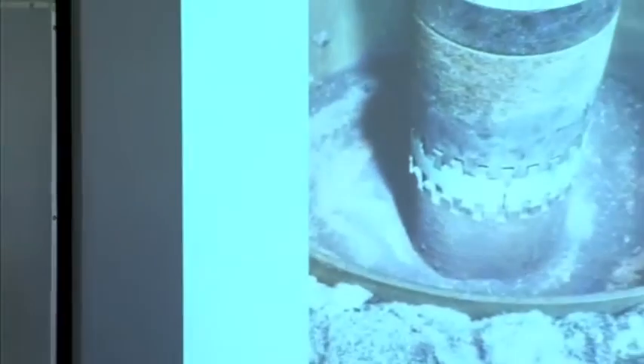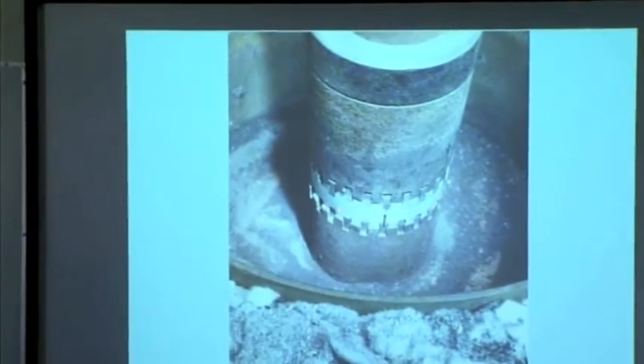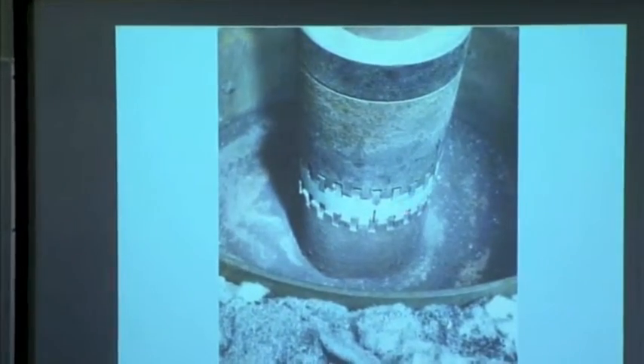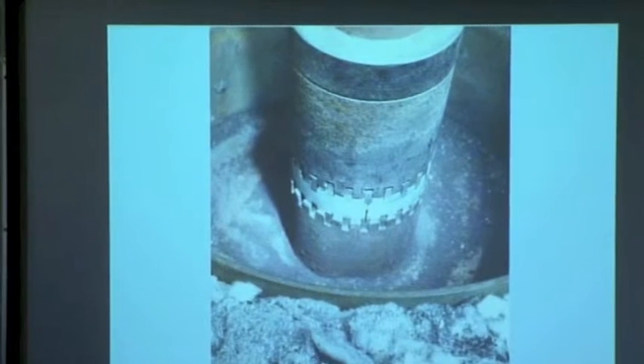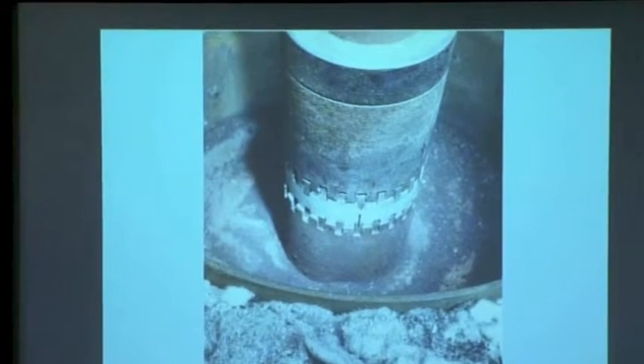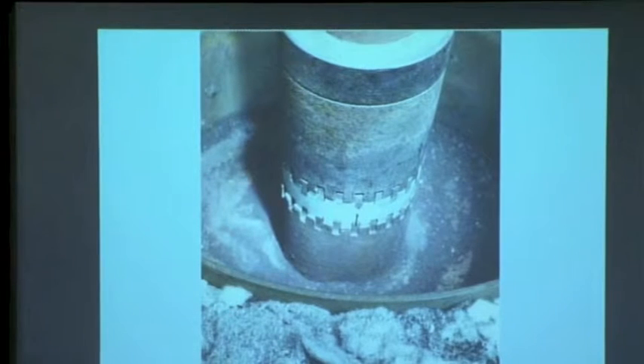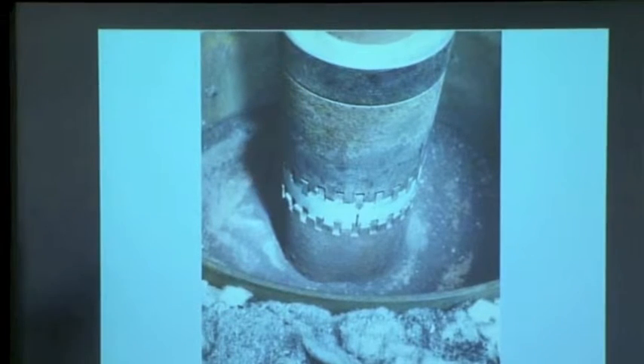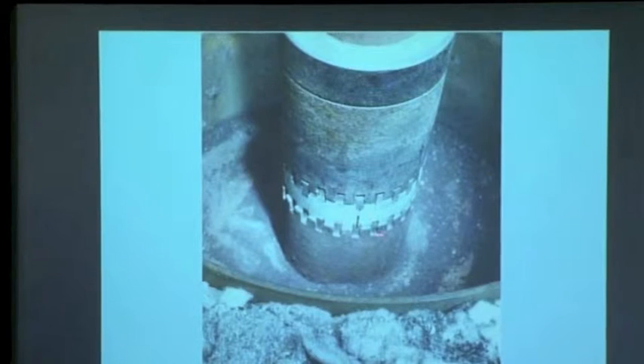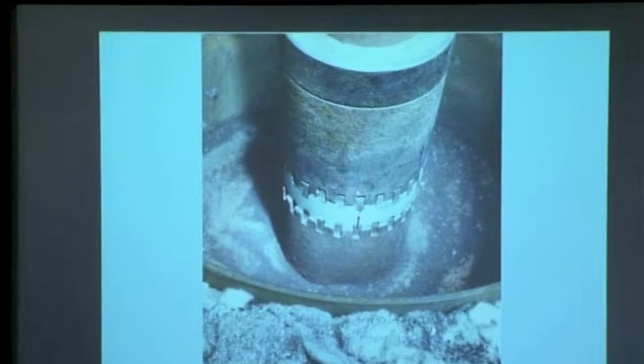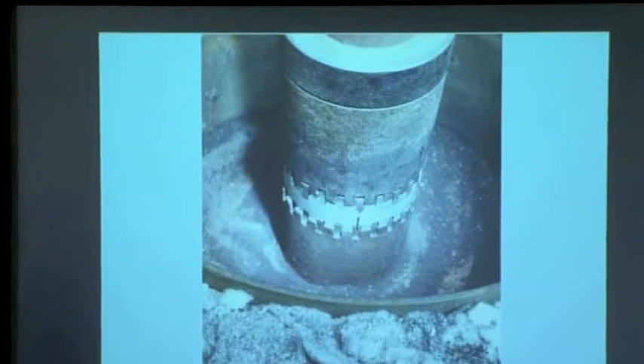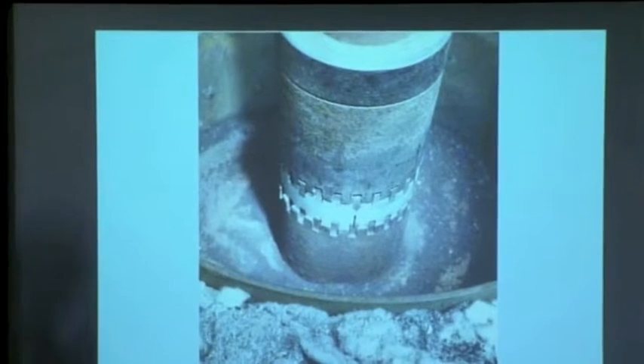So we have begun, this is now ongoing, we have begun to learn about deformation. What we do is we take our directionally solidified zinc tin samples, that's this here, so that has that kind of microstructure that I showed you in the previous slide. And the question then is, what happens if you then begin to deform it? So this goes into a furnace that we built, and you can see these little gripping teeth, and we give it a very small strain rate, which we monitor, and we measure the torque as we do this.